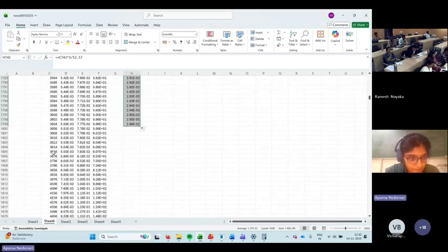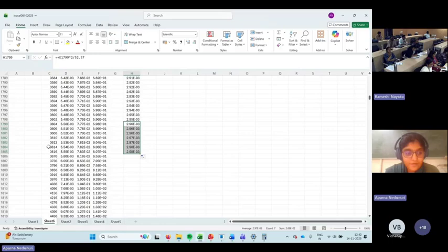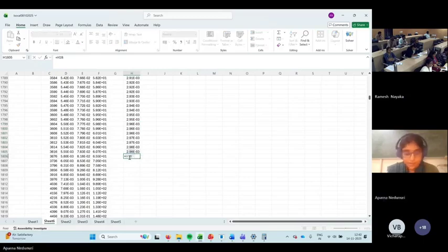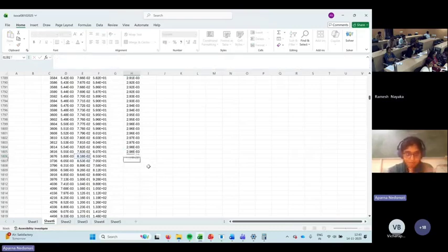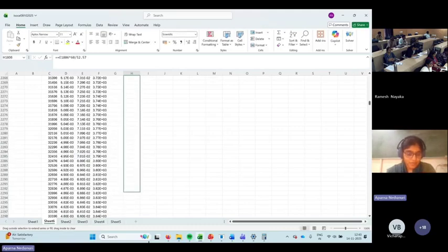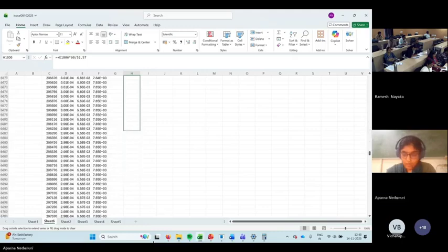So till here we have a 2 seconds interval. From there, I have a 60 seconds interval. So for this data, I'll take the same formula, but instead of multiplying with seconds as 2, I'll multiply this with 60 now, because the interval is 60. Now that is kept constant till the end of your experiment. This would give the value of joule per gram.